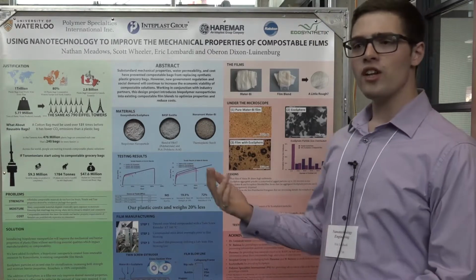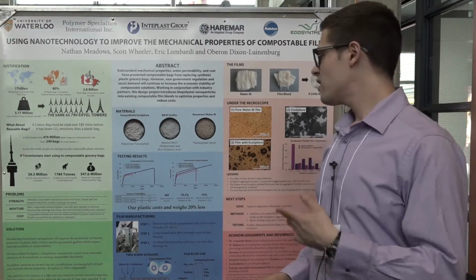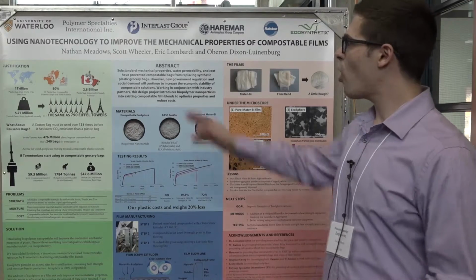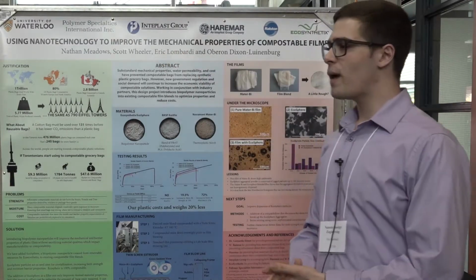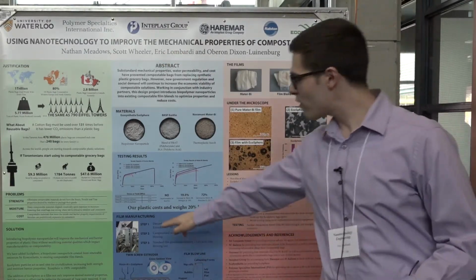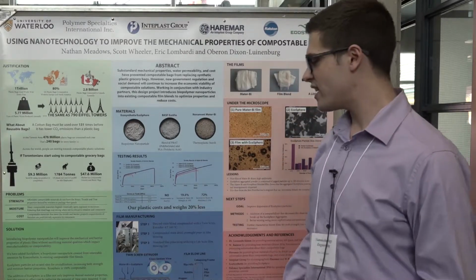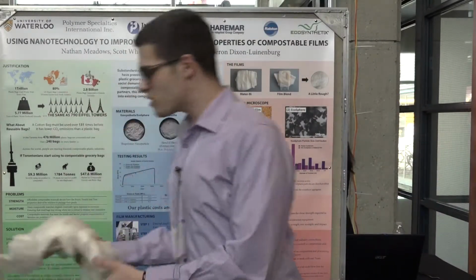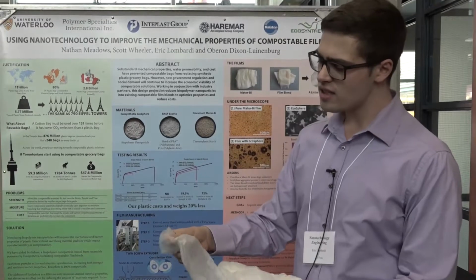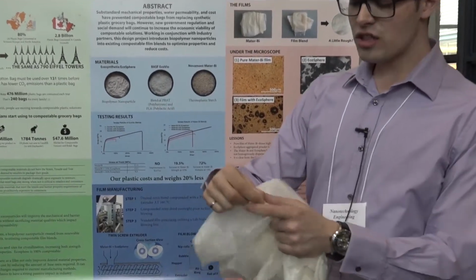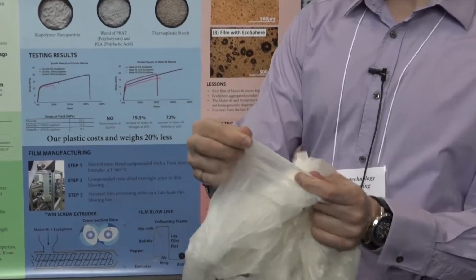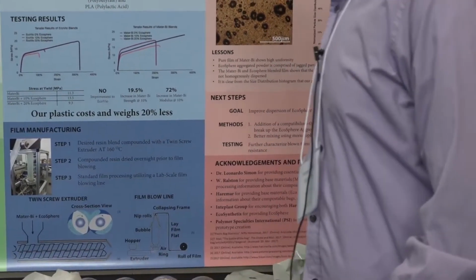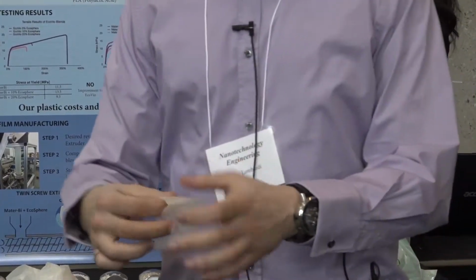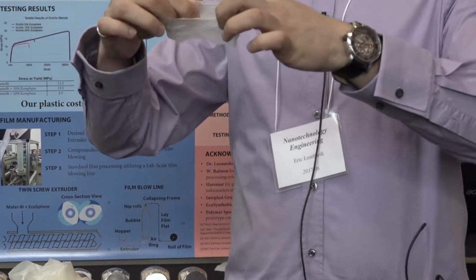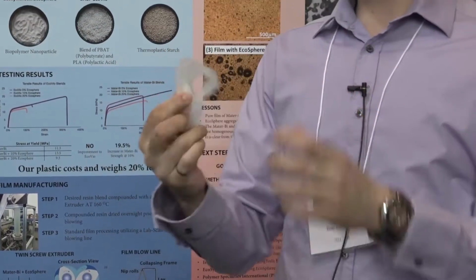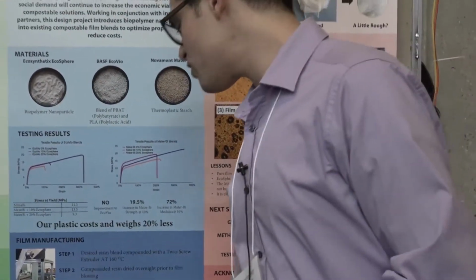With the blend that we knew we wanted to target and our previous blend, we went and worked with Polymer Specialties International, which is based out of Newmarket, Ontario, and went to their lab blow line to blow these films, which we see here. This is the regular film, unprocessed. If you feel it, it stretches relatively quickly. But if we use our film, which you can see here, it's much tougher. And you can feel that toughness because of the nanoparticles we introduced.